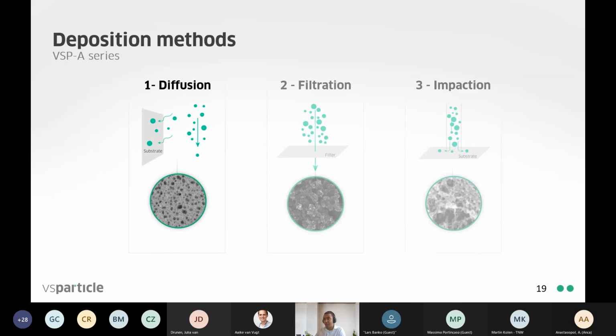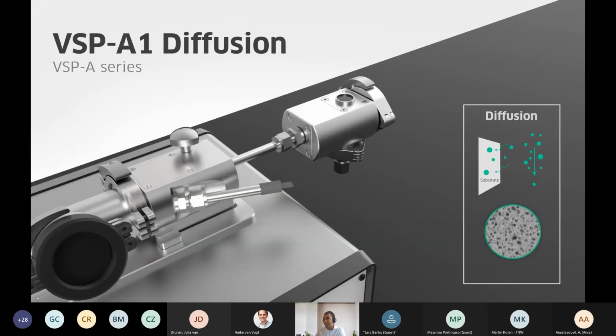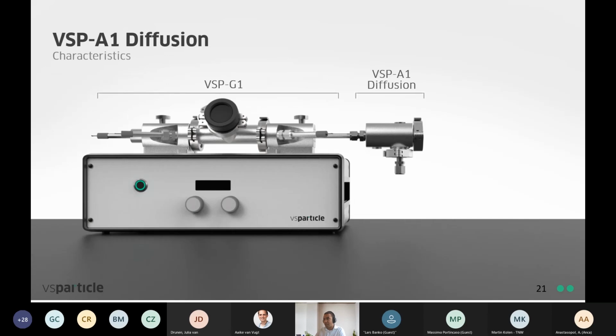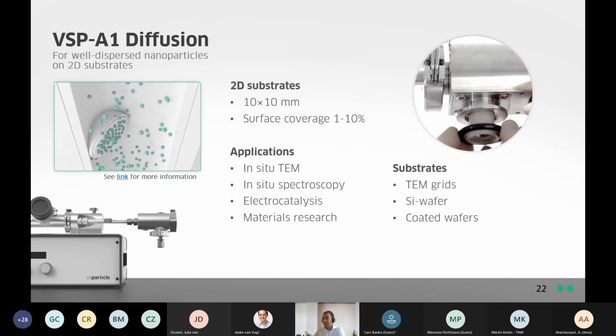So first, the VSP-A1 Diffusion accessory. As you can see, this accessory just slots onto the end of our VSP-G1 nanoparticle generator. So we have our gas inlet here on the left, collecting our nanoparticles in the reactor head, and these are then deposited within the diffusion chamber on a substrate, which is held by a substrate holder. The diffusion accessory uses Brownian motion and the random motion of these particles to deposit the nanoparticles on substrates.